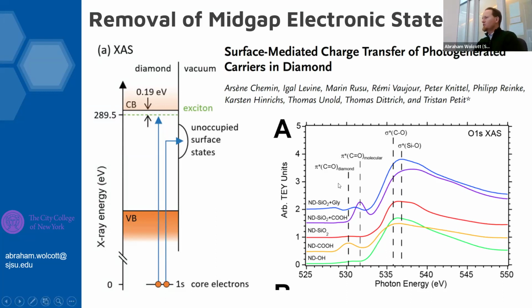For us, I want you to look here at some oxygen XAS, where we've got our oxygen-rich diamond, but it's alcohols, and we don't have C double bond O. We then do our chemistry to put in the acid, and we now have our pi star C double bond O states, which reside here inside of the band gap. Then we generate our silica shell. Those states are now removed. You've cleaned the surface of unoccupied surface states, which can host electrons.